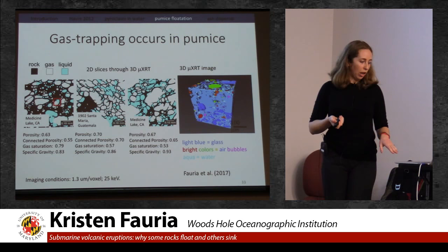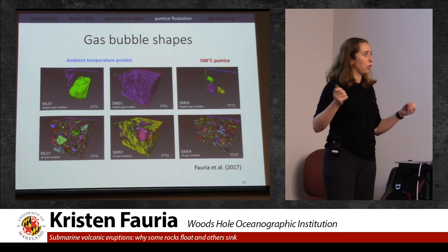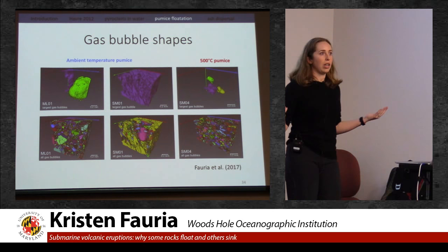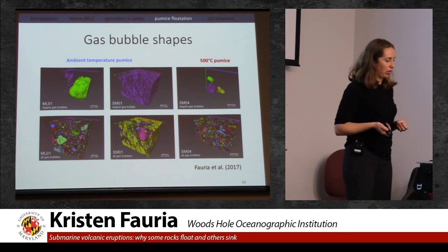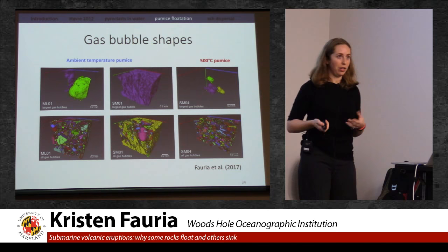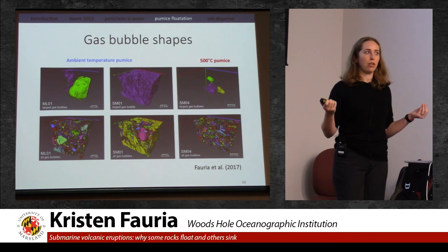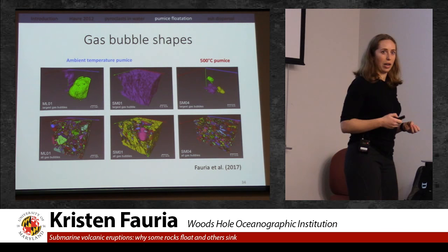And so I just want to show you the shapes of the different gas bubbles inside. We see a range of shapes from these interconnected ganglia to big isolated gas bubbles to many small isolated gas bubbles. So there's a range of different geometries that we see. We do find that hot pumice traps less gas than ambient temperature pumice. But in general, we find that the gas trapping via the capillary processes and surface tension traps enough gas to allow pumice to float for long periods of time, months to years.